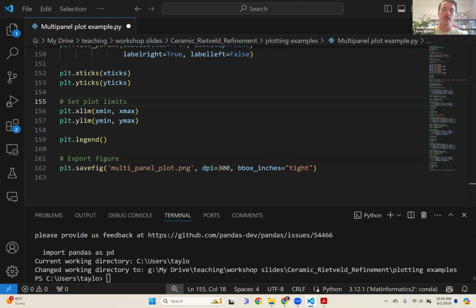You can't do powder diffraction and report a new structure, or nobody's going to take it seriously because you can't accurately refine all the information that you care about. And it's oftentimes ambiguous. Multiple different phases can generate almost the same powder diffraction pattern. We have a good example of that with Heuslers: half Heuslers and superstructures of rock salt can all basically give the same powder diffraction pattern, but they will not give the same single crystal pattern.